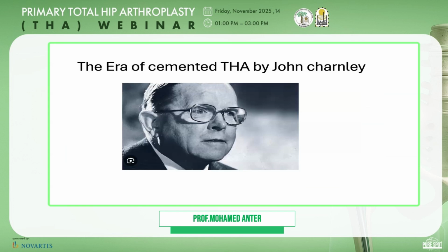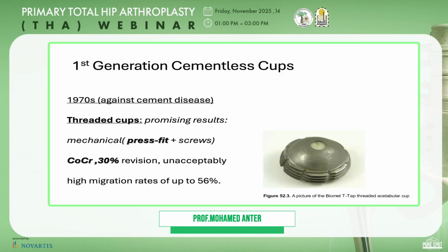Then we came up with the era of the cemented total hip by John Charnley, in which the cementless have declined. Then we came up again with the cementless at the early 70s because of the cement disease with the threaded cups. It had promising results. However, it has about 30% revision rate and a high migration rate up to 56%. Also, the first generation cementless cup depends only on the mechanical fit, no biological fit.